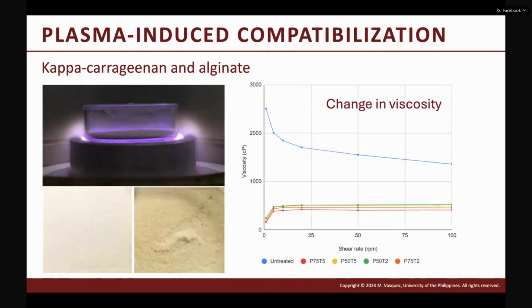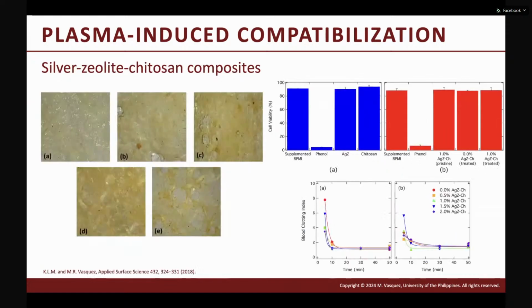Another ongoing work that we're doing now is kappa carrageenan and alginate. These are again natural materials, and we want to modify them for processability. Before, it's difficult to process this because of its high viscosity, but once we pre-treat the material, viscosity now is controllable, and that means processability is also controllable. So we also have this chitosan composites.